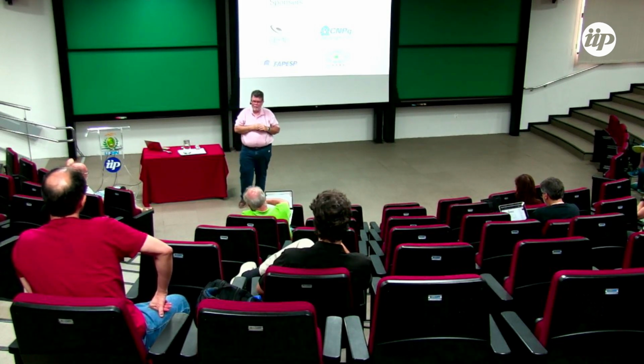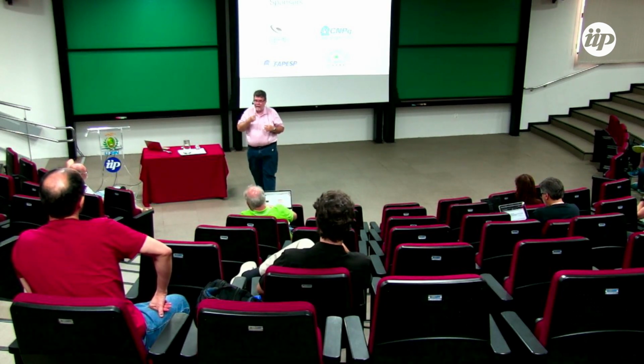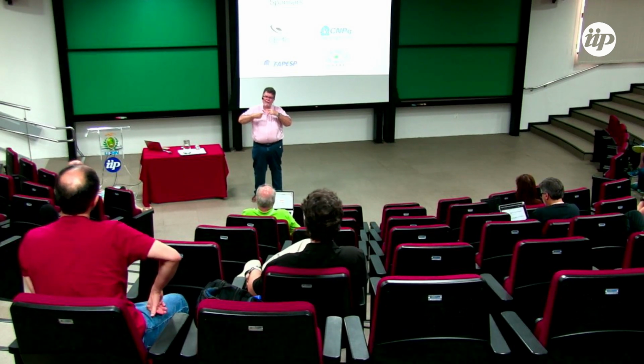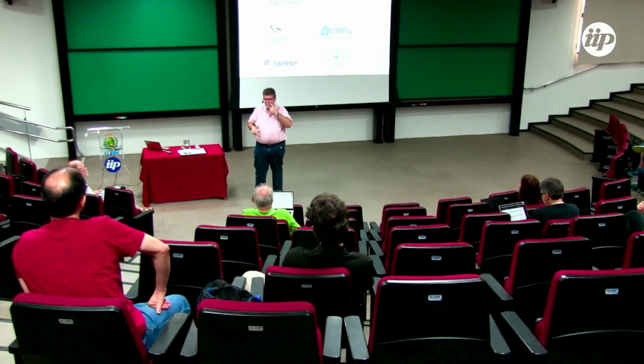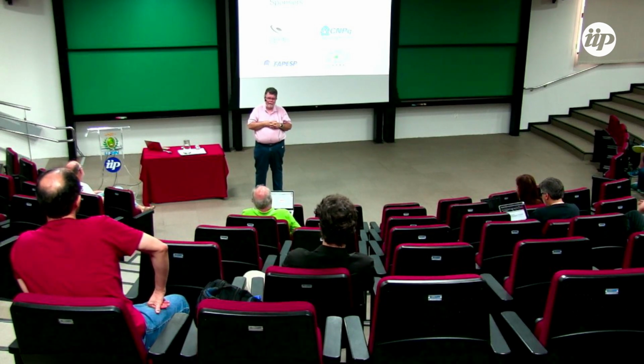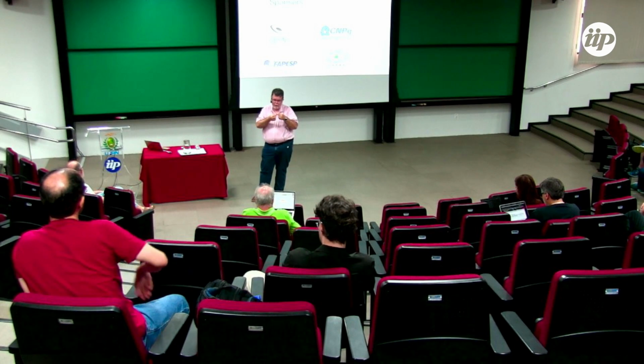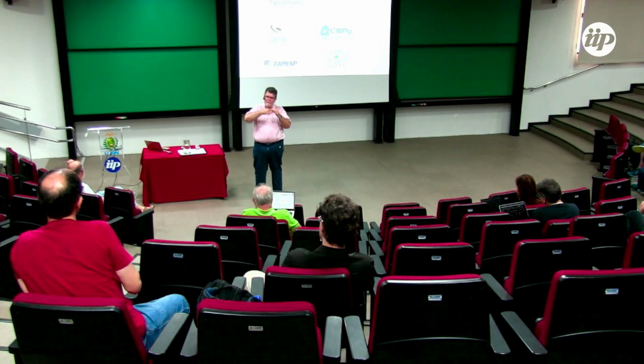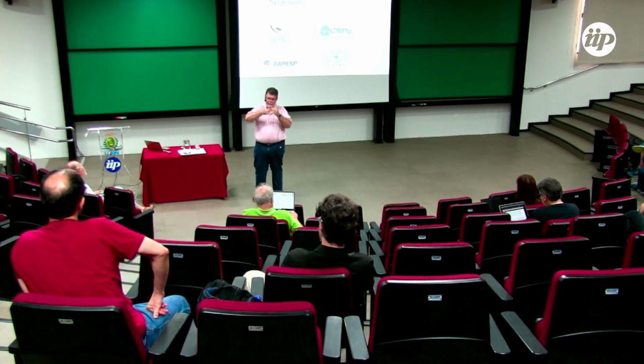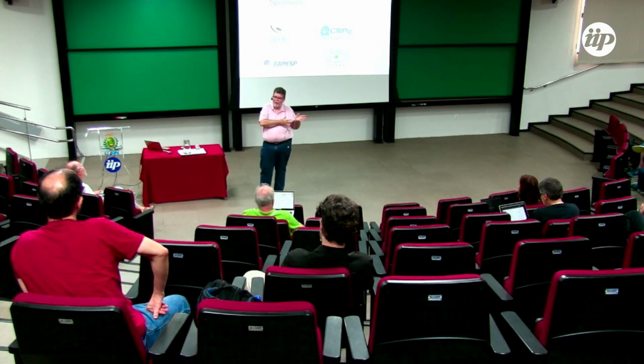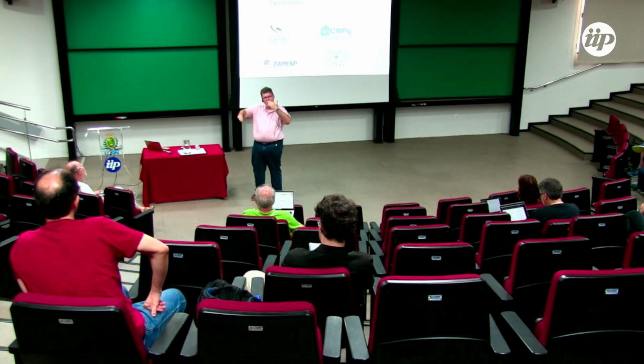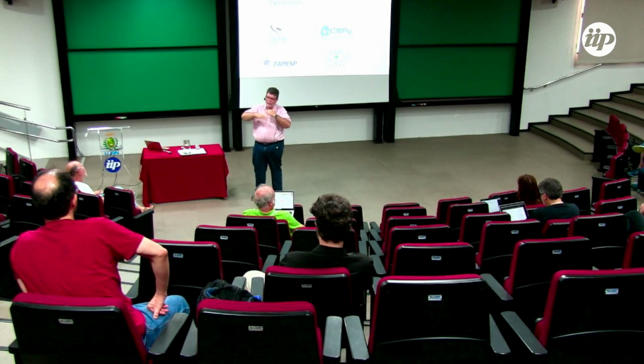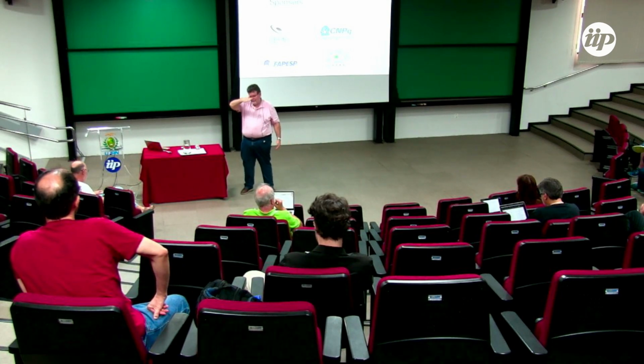much bigger compared to the chromium signal. Interesting. However, I performed relaxation measurements as a function of time. Yeah, I have many data that I have not worked on. In these measurements, we apply magnetic fields, stabilize the temperature, and observe the dependence of the magnetization as a function of time. Above the Néel temperature, with local magnetic moments, we observe the relaxation process. When measured during 2 hours, for example, the magnetization decrease is beyond the error bar. Yeah, it is a good behavior. It is associated with a dynamic process.